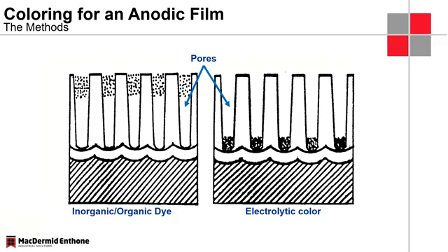Also, they're a lot closer to UV radiation, therefore the light fastness is a little bit limited when it comes to these organic dyes. On the other side, if you look at the electrolytic colors here, they're deposited right at the bottom of these pores. The whole top part of the pore will get sealed and will close up, and it would take a long time for abrasion to actually get to this bottom part of the pore to influence the color depth or the color shade of these colors. So therefore, electrolytic colors, more cost intensive, obviously, to apply, but for outdoor applications, really the best choice.